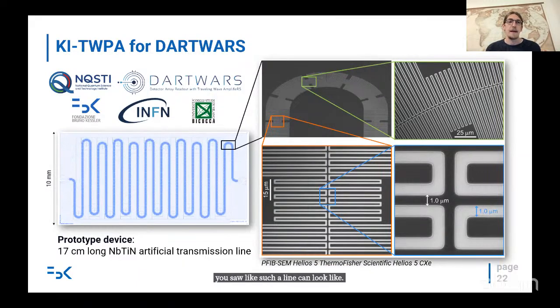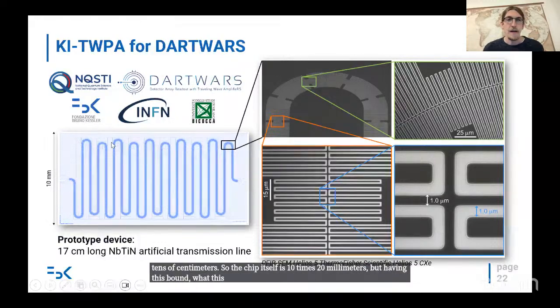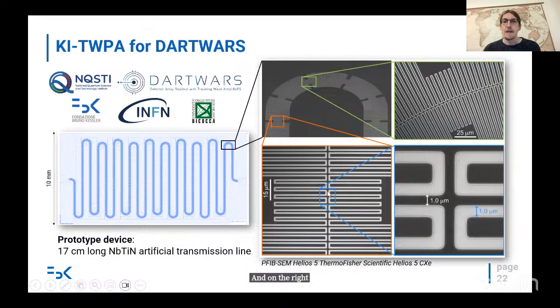They are often in the order of tens of centimeters. So the chip itself is 10 by 20 millimeters, but having this meandering structure, you actually end up with a device that has a length of order 17 centimeters. And on the right side, you see electron microscope images of how such a line actually looks, where you see in dark the actual metal, and in white the substrate where the metal has been removed with an etching technique.